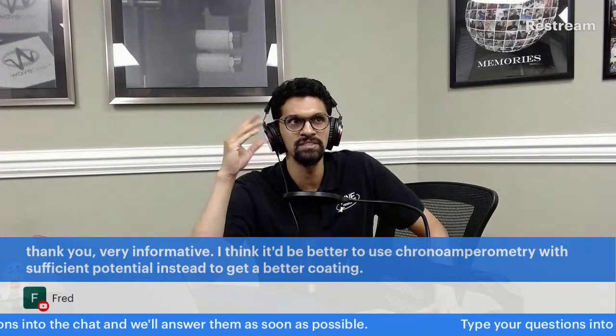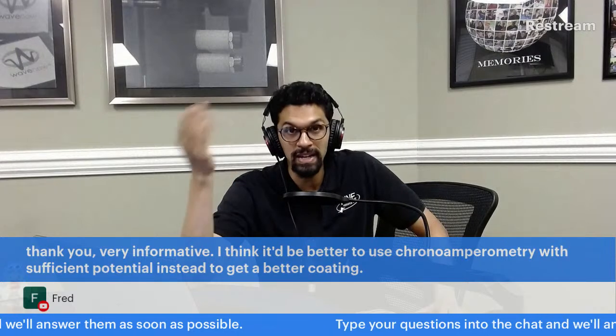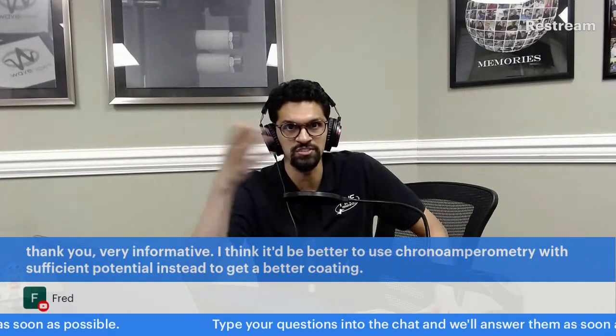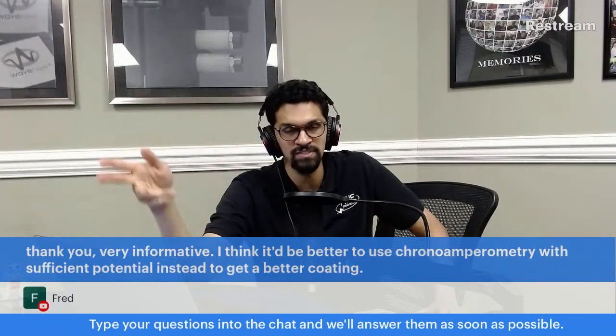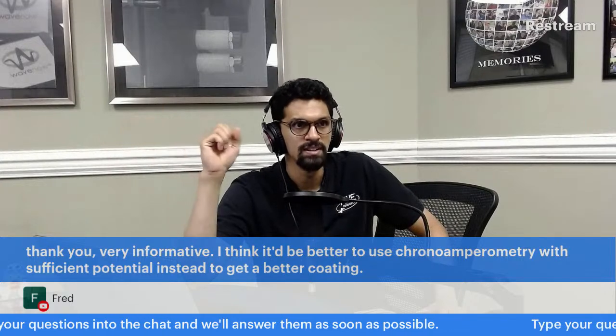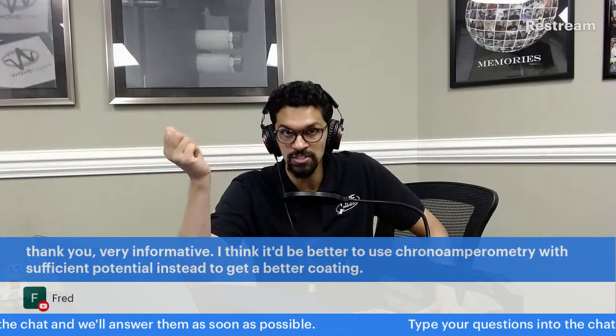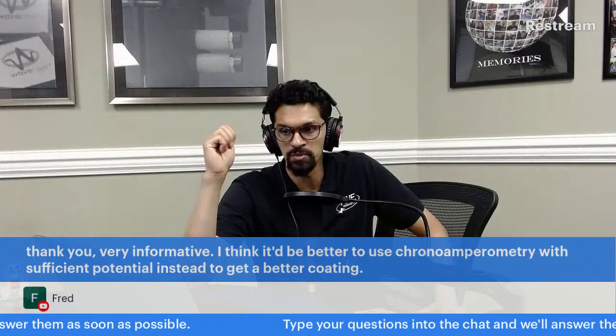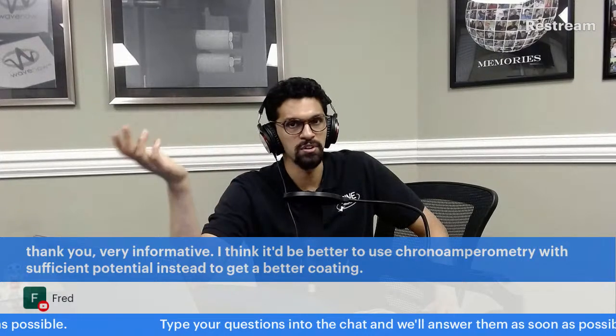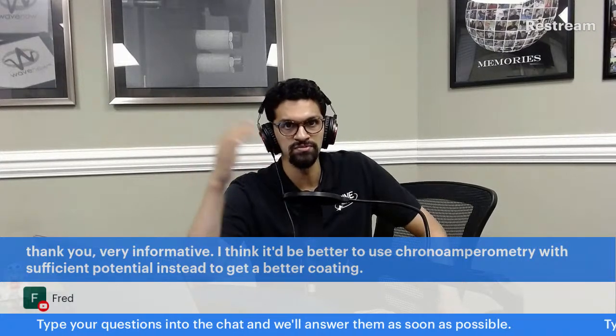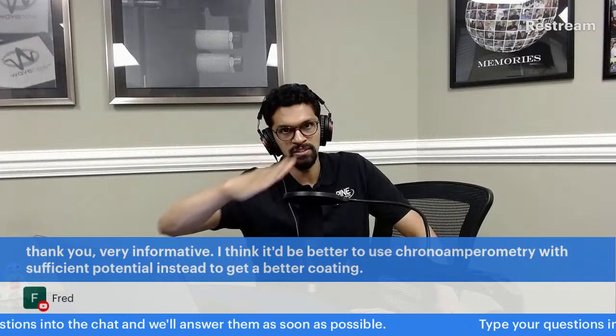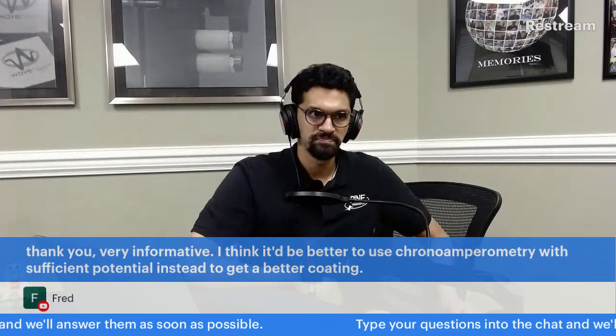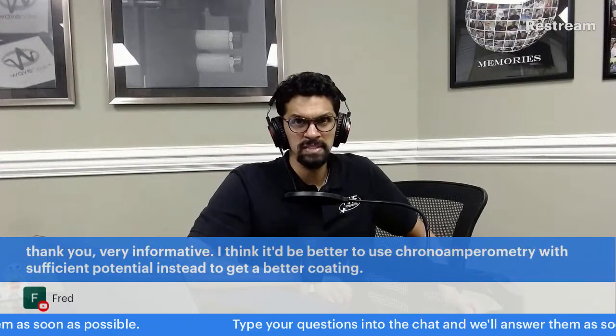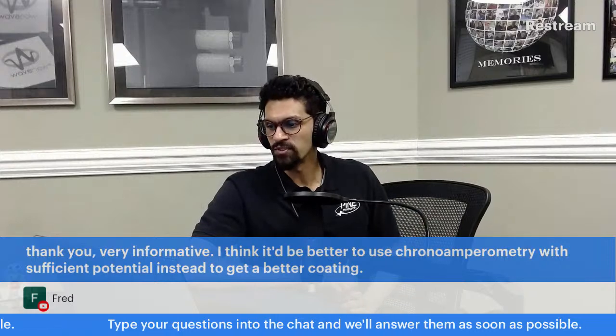But you will quickly find that the rate can change, the current can change, so the rate of the deposition can also change. And maybe the rate of the deposition is very important to getting a homogeneous coating. If you do chronoamperometry in a typical configuration, it starts high and then it goes very low. So it might not be something that you want.